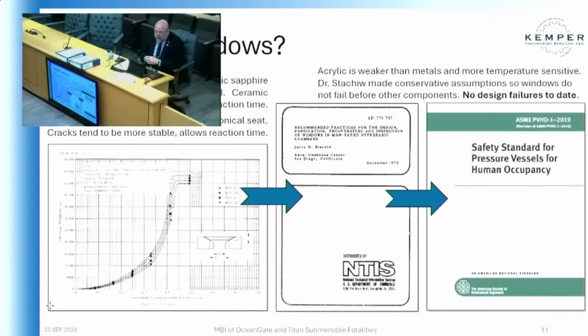So that was the process used. And the significance of this is that to date, as of today, we have yet to have a PVHO-1 window that was manufactured to standard and put in properly and not see an abuse. In other words, you weren't a submarine that took your window down to a thermal vent. You didn't decide to put a heat lamp next to a window to warm someone up. As long as you don't do those things, there have been no design failures.